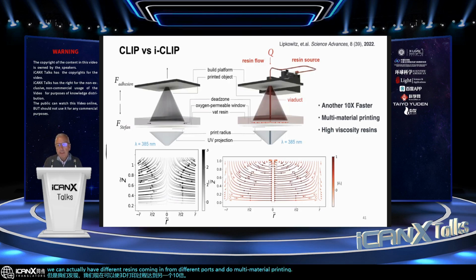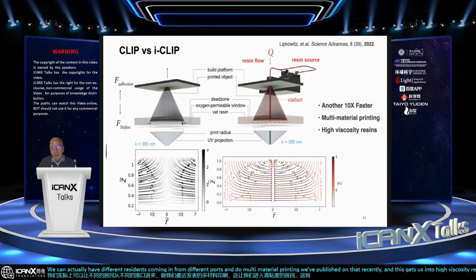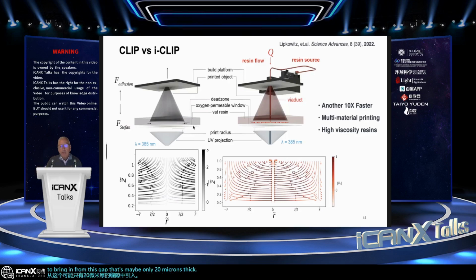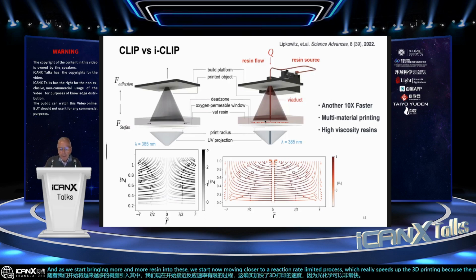We've published on that recently. And this gets us into high viscosity resins that would be arguably hard to bring in from this gap that's maybe only 20 microns thick. And so the chemistry here historically has been a mass transfer limited process. And as we start bringing more and more resin into these, we start now moving closer to a reaction rate limited process, which really speeds up the 3D printing, because the photochemistry can go really fast. So we published on this. We're excited about this. I'm not going to dive too much into this,